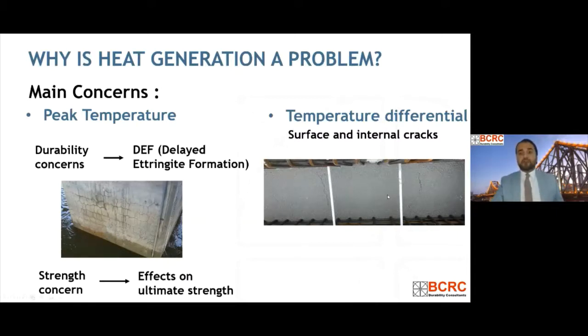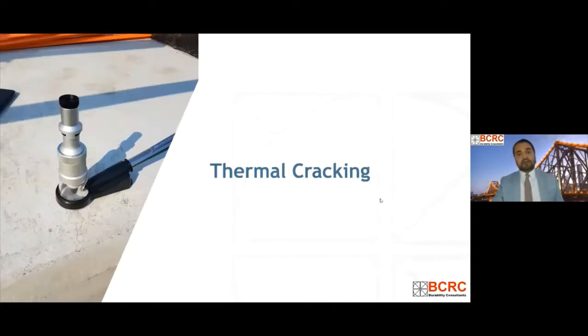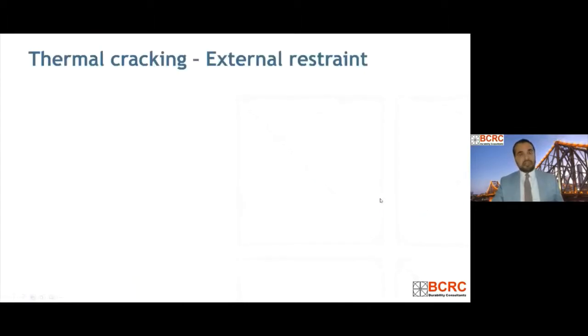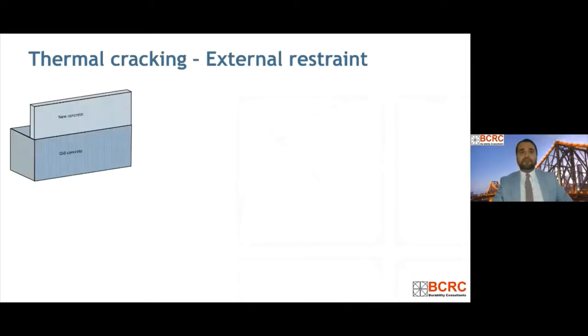So now we look at the thermal cracking. Thermal cracking can be either due to external restraint, or it can be due to an internal restraint, right? Let's first look at the mechanism behind the external restraint cracking. We can see here that this is an old concrete, and we are casting a new concrete on top of that. So it could be a pile cap or a headstock, and this is a small thin wall.